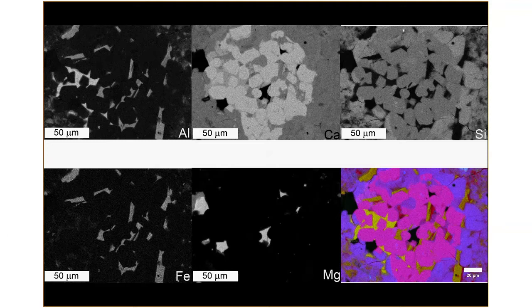Calcium is the brightest coloration in the center image, showing you where those calcium silicates are. We move to silicate in the upper right hand, and you see the silicates lighting up. The iron phase down in the lower left, you see where the iron of the ferrite phases light up. Magnesium, which is not all that exciting to be in concrete, we see a fair amount of that, and then we get this false color imagery in the lower right-hand side.